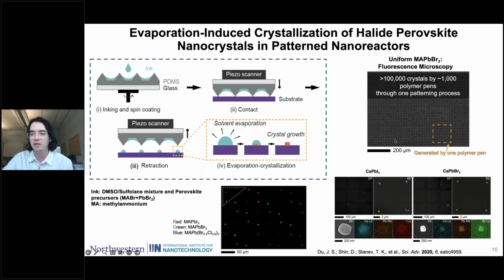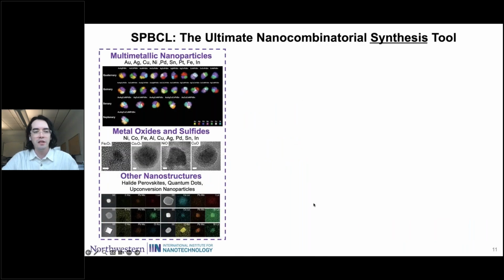And so you can see images again showing arrays of these perovskites. We can tune the composition by putting in different anions or cations, and then we can also pattern multiple materials on the same substrate. So in this case, we can construct an RGB array of perovskites. And so what we have at this point is a very powerful synthesis tool to do nanocombinatorics. So we can make lots of unique structures, putting lots of different elements into the design.